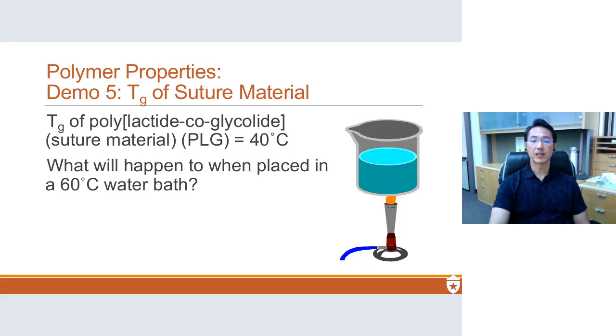So for my next demonstration, I used to do a demonstration with suture material. Polylactic co-glycolic acid is a suture material, and what I did was I made a really nice puck out of this, and it was a very glassy puck. And I had students come down and try to break it or bend it, which they couldn't. And then I left it in a 60-degree water bath. And after that, you can see that it was very leathery. Unfortunately, one year I had this really buff guy, almost as strong as me, and he came down and actually broke the thing. So I no longer have this demonstration.